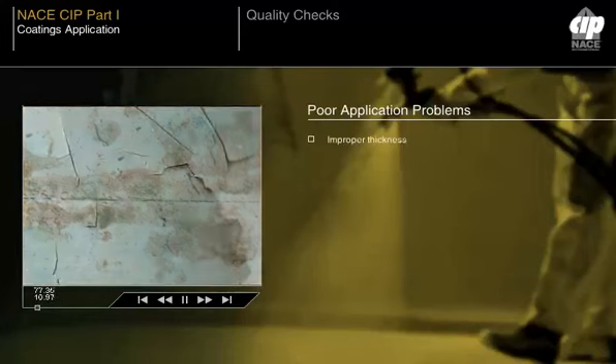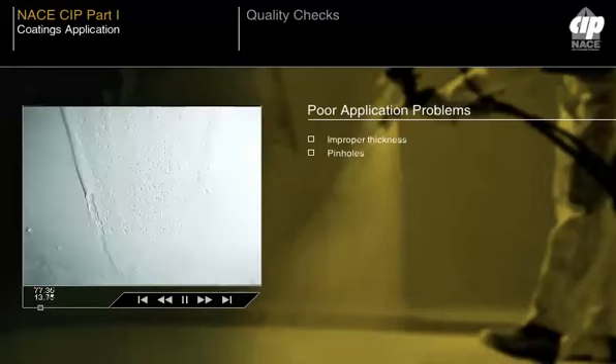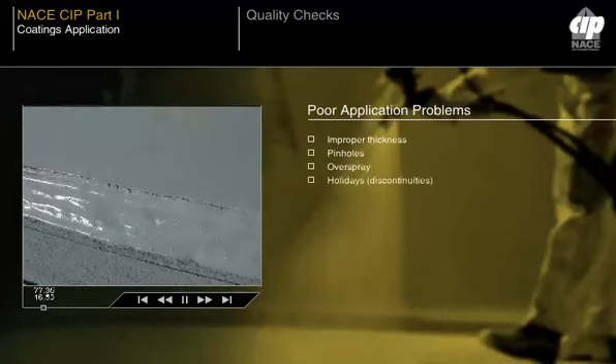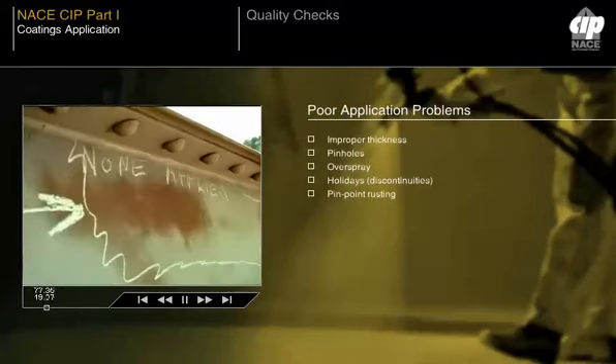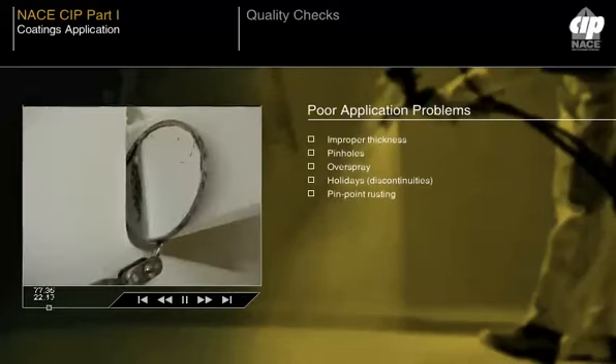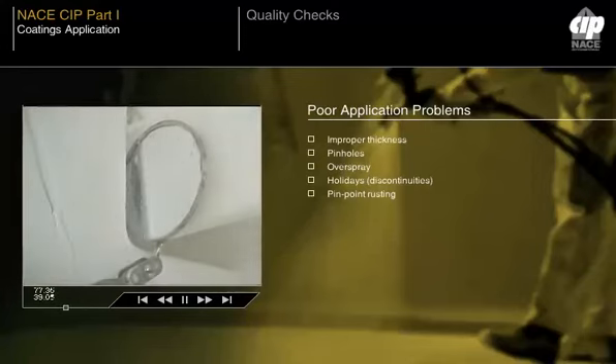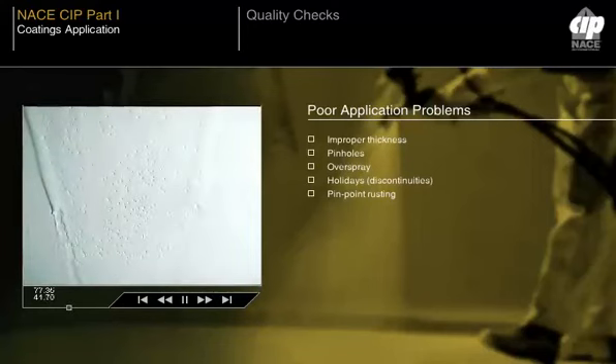Poor coating application is a major factor which causes failure. Typical problems resulting from faulty application techniques might include improper thickness, pinholes, overspray, holidays, discontinuities, pinpoint rusting. Almost all application-related failures are due to poor workmanship, though this may sound like harsh judgment. Poor workmanship refers to such practical issues as holding the spray gun too close or too far away from the surface, or at a significant angle to the surface being coated.